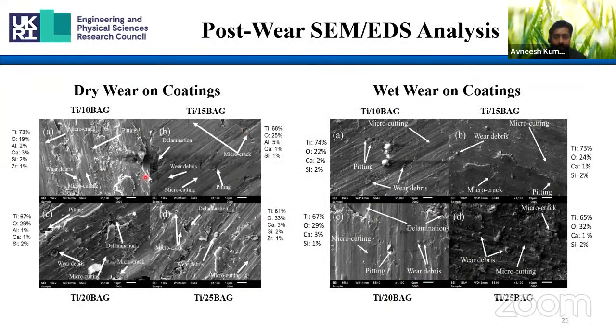So these are the coatings after post wear analysis. This is under dry condition and this is under wet condition. In all the coatings, we have observed signatures of micro cracks, pittings, micro cuttings, and wear debris also. These wear debris are smaller in size than the particles we used earlier for spraying, and they may have taken part in abrasion. That can be a third body type of abrasion, which has influenced the wear rate also. So these features are common in every case, and I think they are the reason for the high wear rate in these coatings.